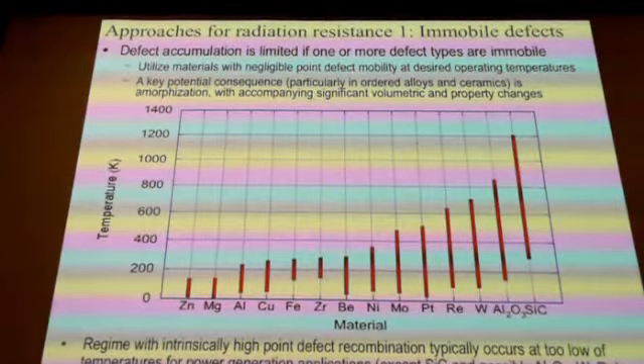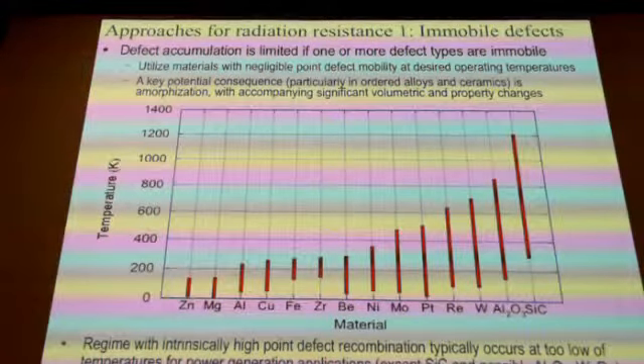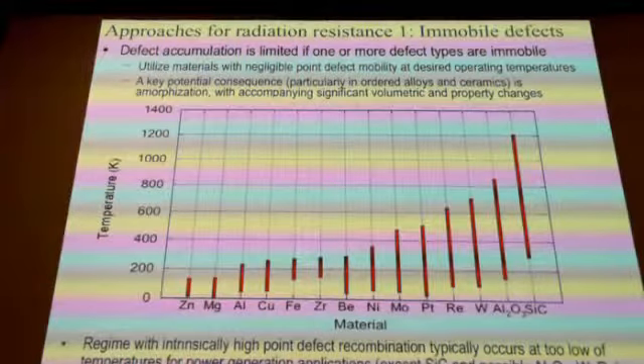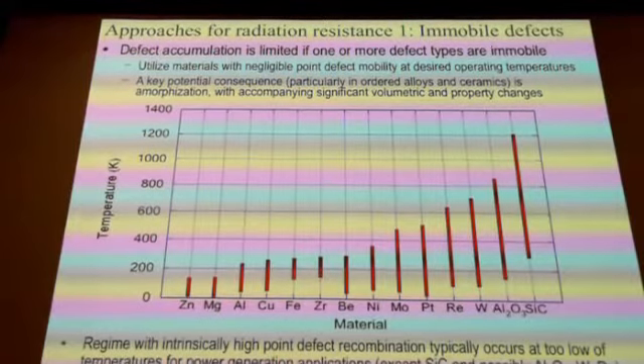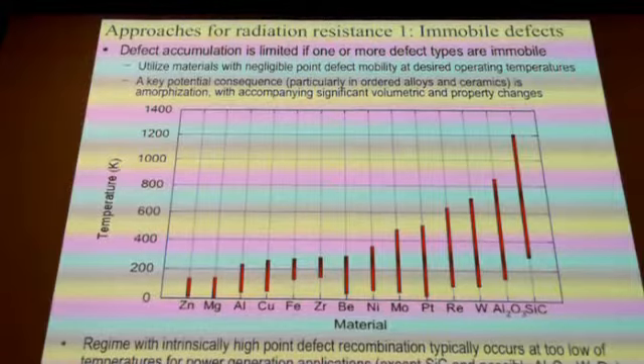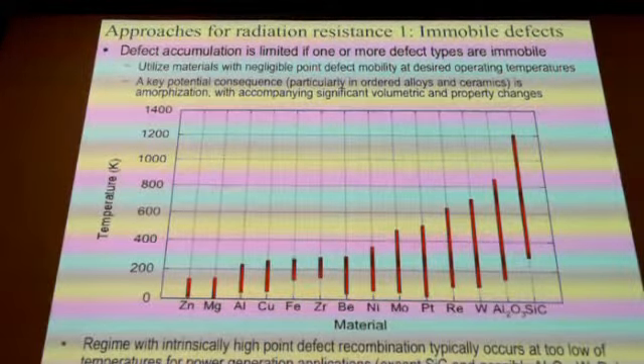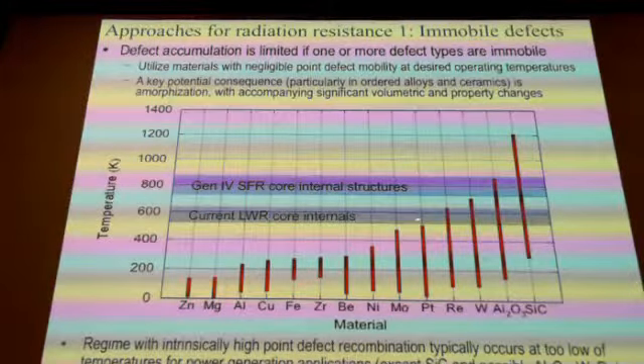The lower extent of the red bar is the onset temperature for interstitial migration. The upper extent of the red bar is the onset temperature for vacancy migration. So anywhere between the lower and upper region of this red bar, all of these materials are going to have extremely good radiation resistance in general, because the interstitials will all recombine with the vacancies that are being produced. That looks fine until you start putting on what temperatures you might want to use these materials at.